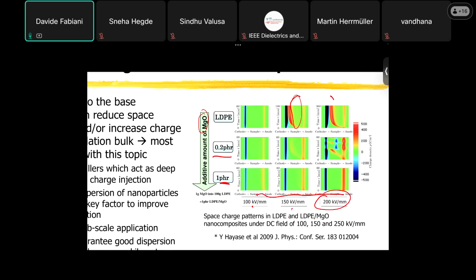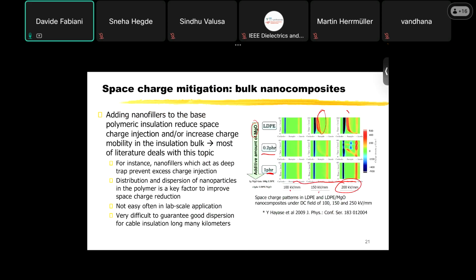So this is one way of suppressing charge injection by creating deep traps. And these deep traps create a sort of barrier for space charge to be injected inside the material. But the problem is that the distribution and the dispersion of the nanoparticles is a key factor if we want to get very good property improvements.